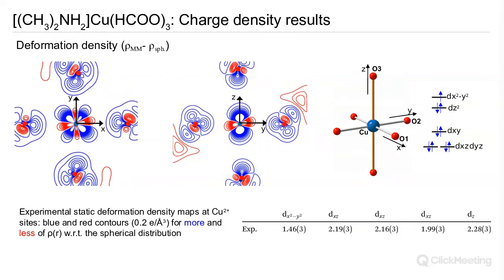Piero highlighted the difficulty in mapping between the orbital occupancies and the charge density, because the charge density is the square. Well, not only is it hybridized with everything else, but it is in the square of the orbitals. But in the case of a coordinated atom where the charge is largely localized on the transition metal, we can do a reasonable job of it. And this mapping was done in this case, and we can see that the x squared minus y squared orbital is roughly half full with a single electron, whereas all the other d orbitals are fully occupied with 2 electrons. So this paints the picture that we expect for this Jahn-Teller distorted copper atom.